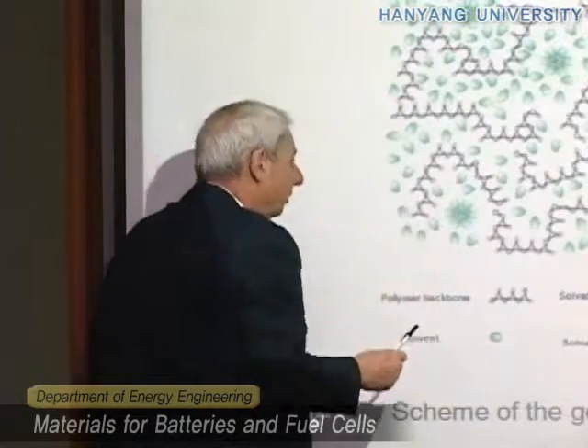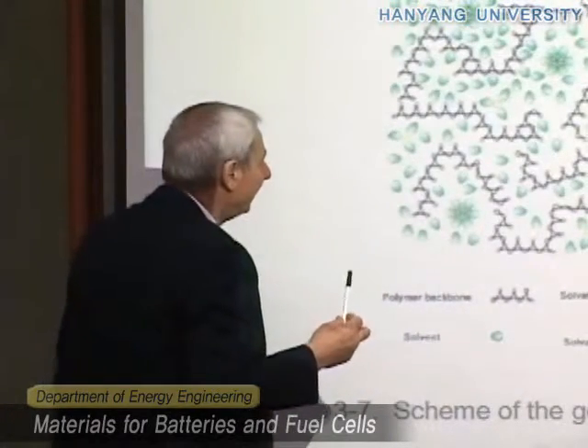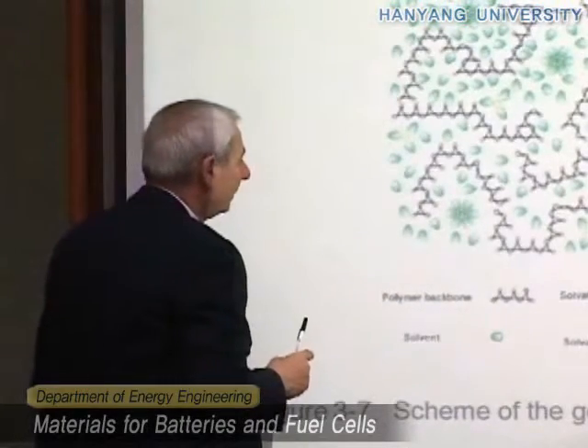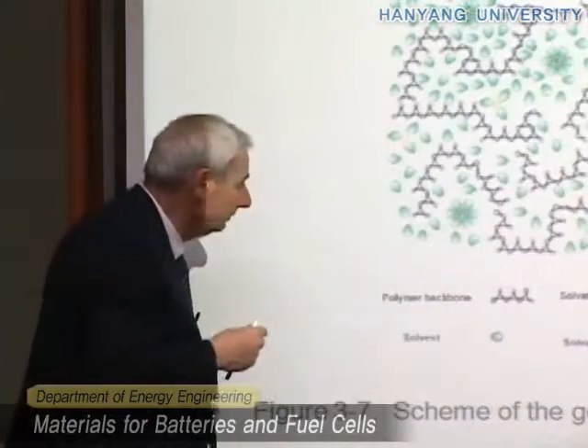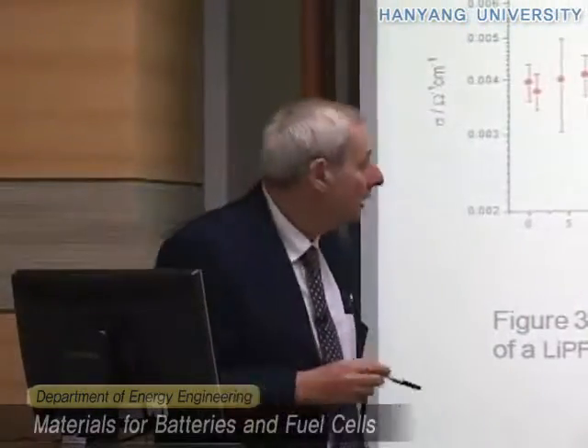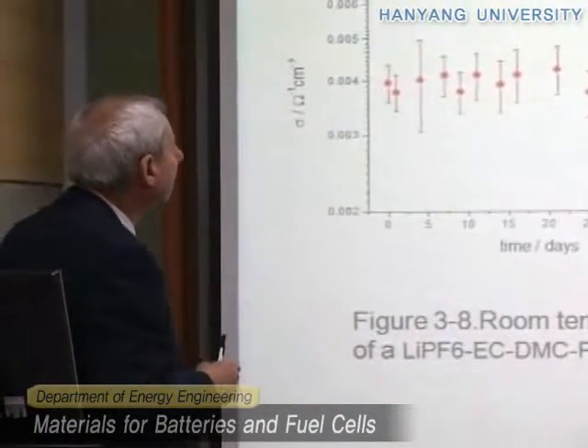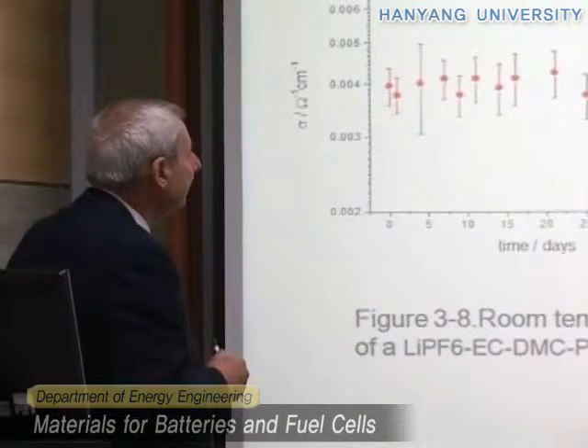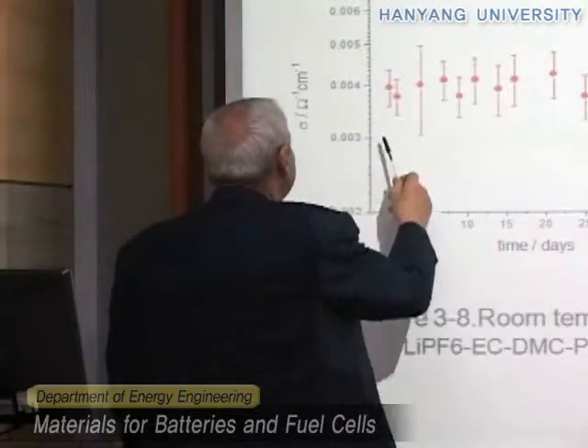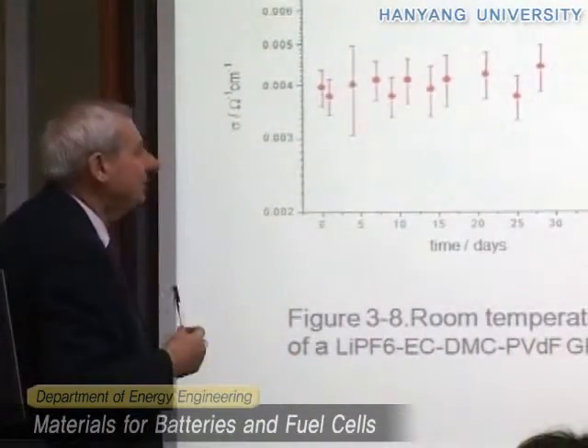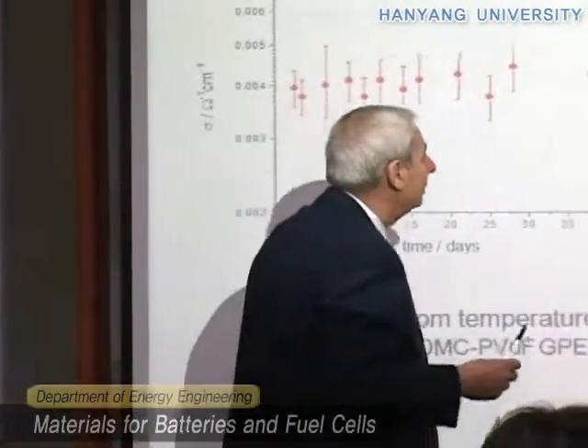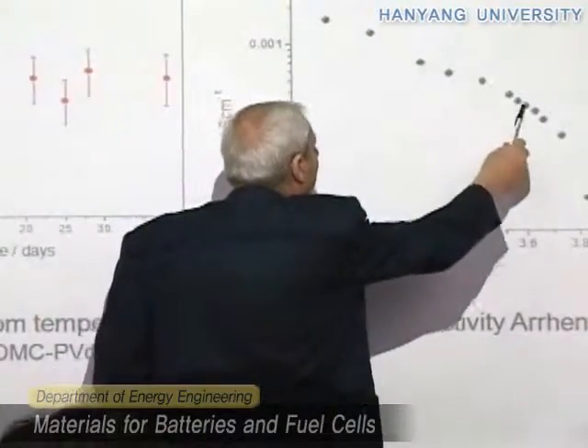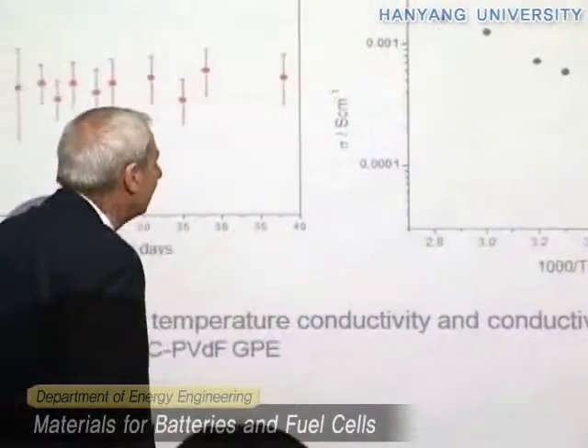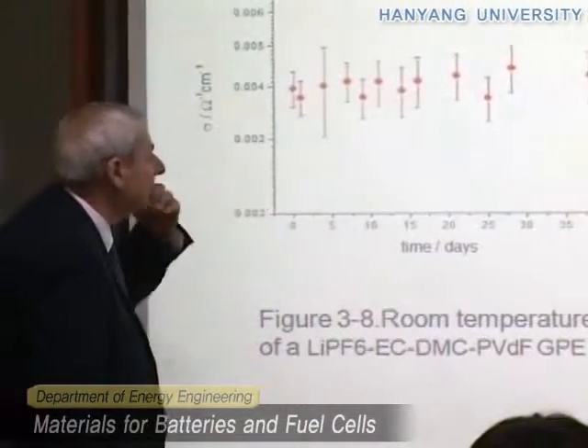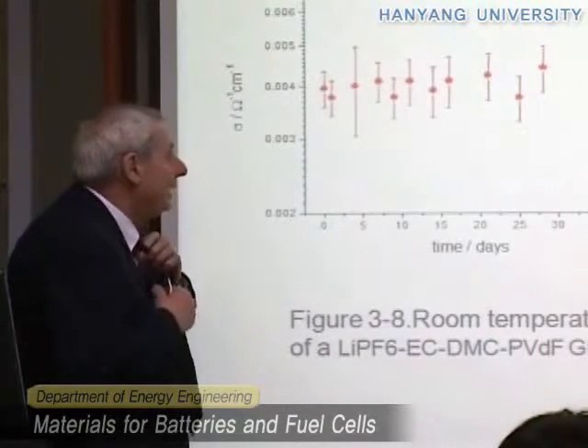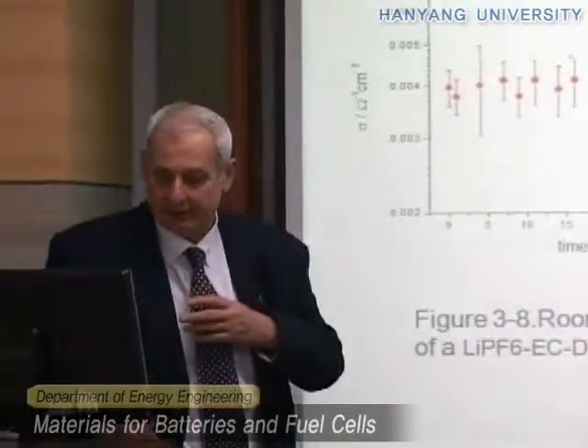However, there are obviously some pores, and one of the problems of this electrolyte is that some of the liquid goes away. Then you lose conductivity. And you see here the conductivity of these typical gel polymer electrolytes, GPEs. And here is the conductivity at room temperature. So we have 4 millisiemens. It's very similar to that of the liquid. And here is the conductivity versus temperature. The conductivity is good up to 0 degrees, but not so good at minus degrees. But nevertheless, at room temperature, the conductivity is pretty good. This is the reason why these gel electrolytes are now used for practical batteries.